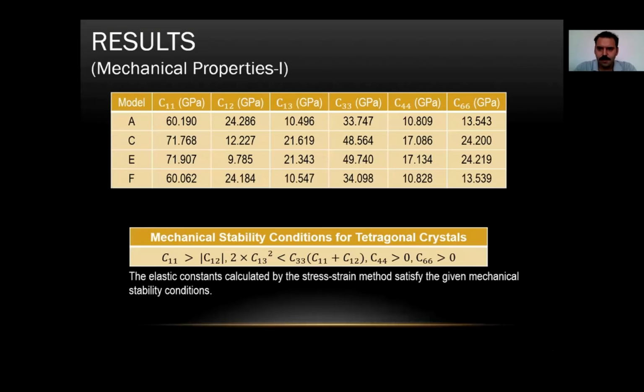Some of the mechanical properties we have obtained as a result of our calculations are given here. The second order elastic constants were calculated for a single crystal using the stress-strain method and are given in the table above. We have seen that these values meet the mechanical stability conditions given for tetragonal structures. This indicates that the material is mechanically stable.